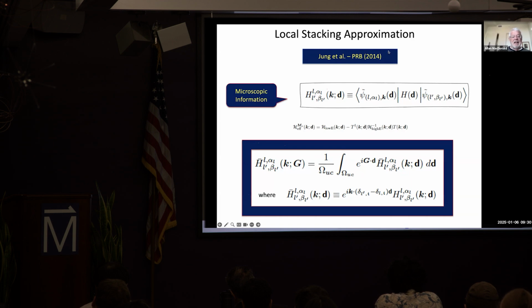The starting point for this approach is to first calculate the Hamiltonian as a function of stacking. D here is the local stacking. For rigid rotation of one layer relative to another, the displacement produced by a rotation is just linear in position. It's only the position modulo lattice vector that's going to matter, but that's a rigid rotation, and you can take into account strain effects. I'll mention that in a minute.